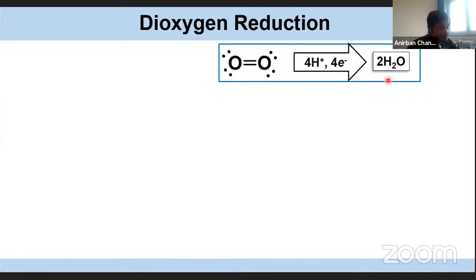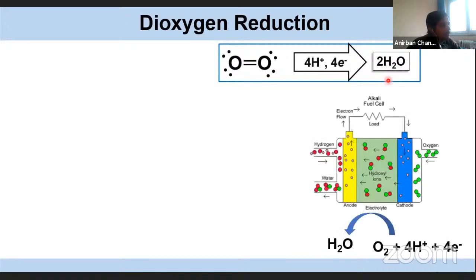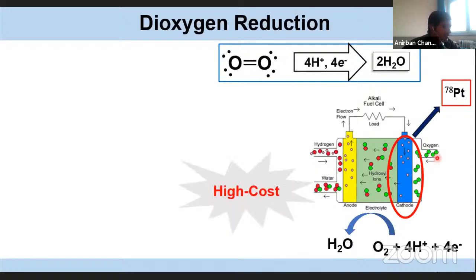It is not only in aerobic respiration but also in the fuel cell, because in a fuel cell the common cathodic reaction is the four electron reduction of oxygen to water. In any kind of fuel cell, mostly hydrogen based or alkali fuel cell, at the anode hydrogen is oxidized to proton, whereas at the cathode oxygen is reduced to water. However, the efficiency of the fuel cell depends on the high loading of platinum metal in the cathode. The more loading of platinum metal is required for the higher reactivity of this fuel cell. And as we know, because of this, the fuel cell becomes more expensive because of the presence of this platinum metal.